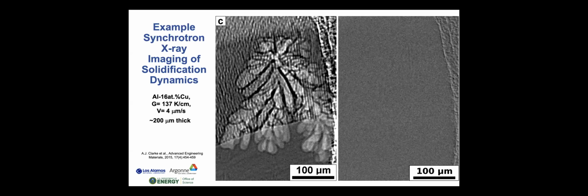So here we're doing synchrotron X-ray imaging. And what you're going to see in this movie that I'm about to play is early stage dendritic growth of an aluminum-rich dendrite in the field of view as we're pushing a planar solid liquid interface from the top down into the field of view. And that aluminum-rich dendrite is actually lower density and it's buoyant.